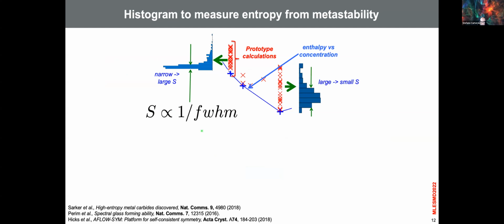So now we have all our thermodynamic excited states, which are all these red dots, and these blue dots are given by the convex hull. Now, how do we define entropy? Well, technically, this is already entropy, but it is not. The generation of these things really indicates entropy, but it is not because we have only calculated a finite number. You should calculate infinite, but of course we do not have infinite computers, so we cannot really do it.